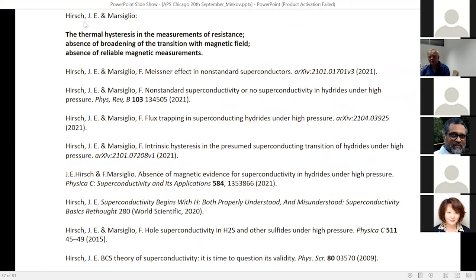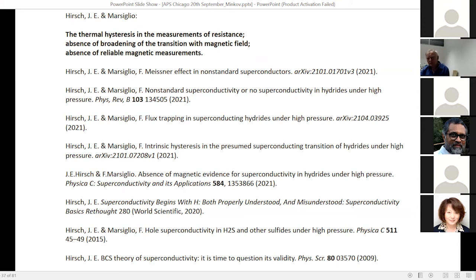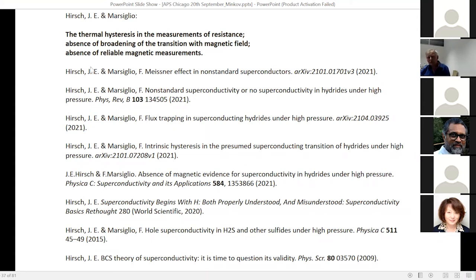Hirsch and Marsiglio have published many papers — even today another one appeared — with criticism which can be summarized as follows. From their view, what is lacking in our experiment: we observe hysteresis which should not appear in a superconductor; no broadening of the transition in a magnetic field, contrary to type-II superconductivity; and most importantly, absence of reliable magnetic susceptibility measurements.